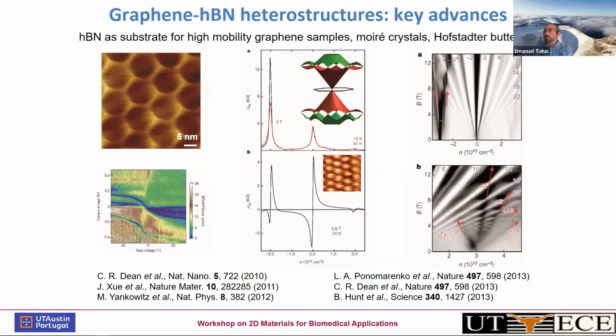Another peculiar property of graphene on hexagonal boron nitride is that because these lattices have a similar lattice constant, something forms here that's called a moiré pattern. That's because there is a superlattice that forms in this particular heterojunction, and that's illustrated here. The wavelength is on the order of 10 nanometers, and as a result, it creates replicas in the band structure. So think of it as having a superlattice.